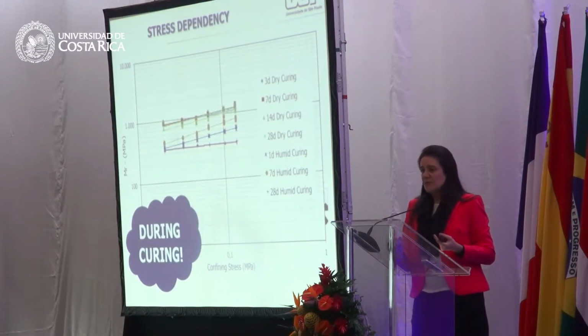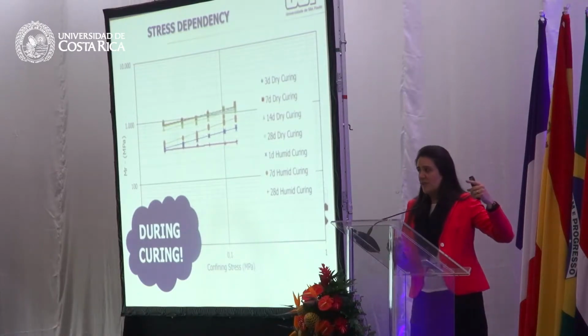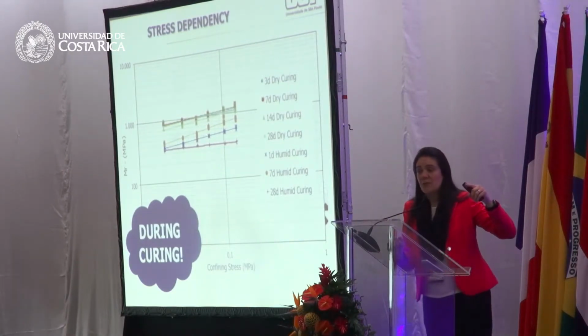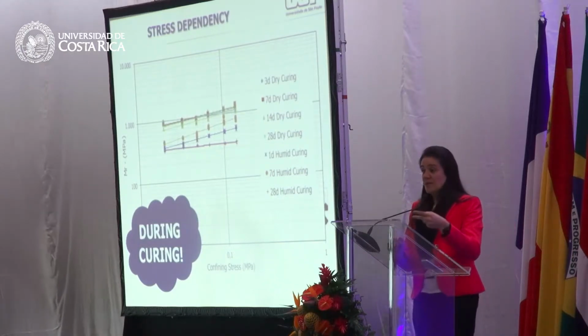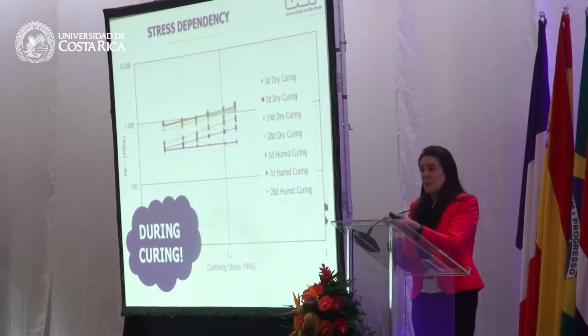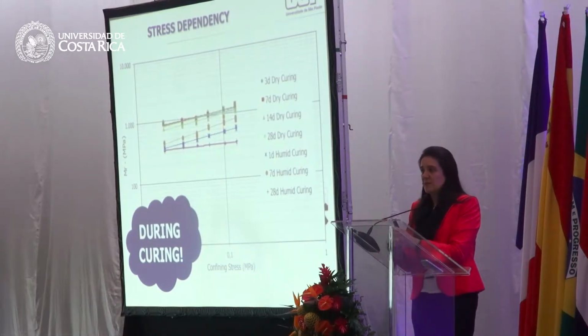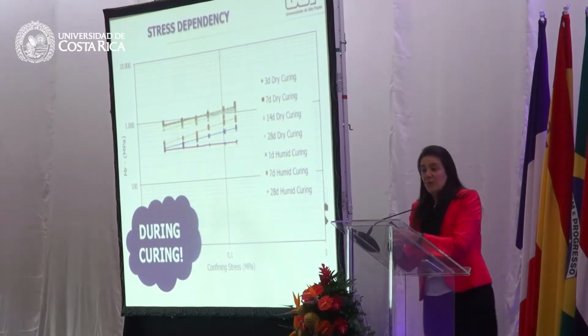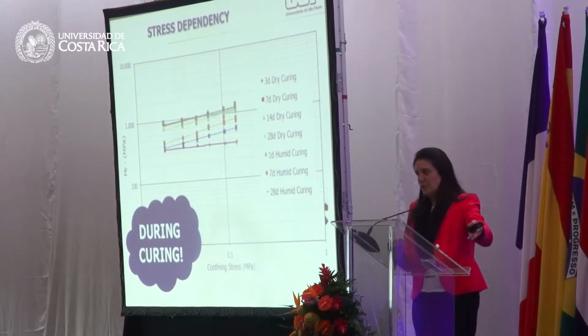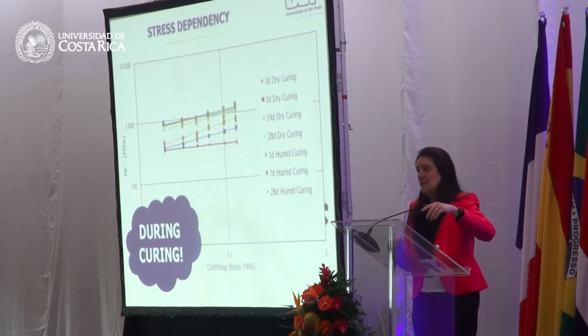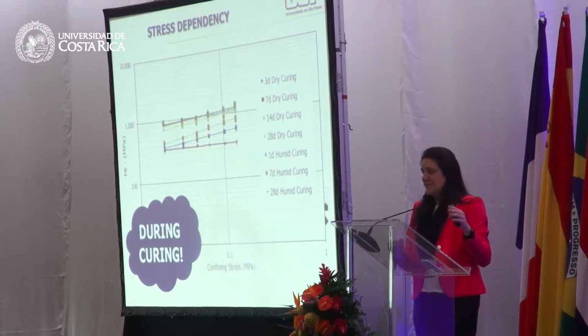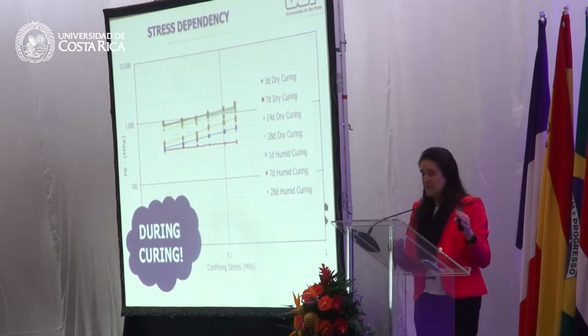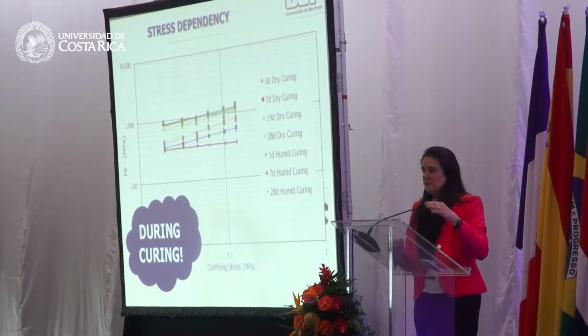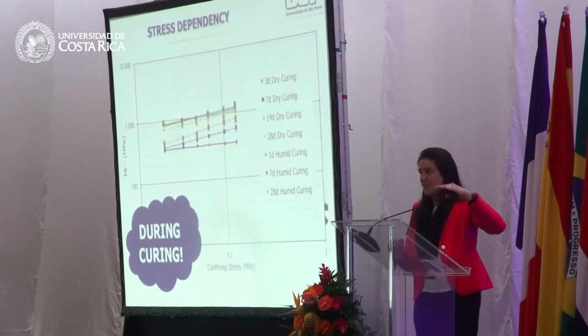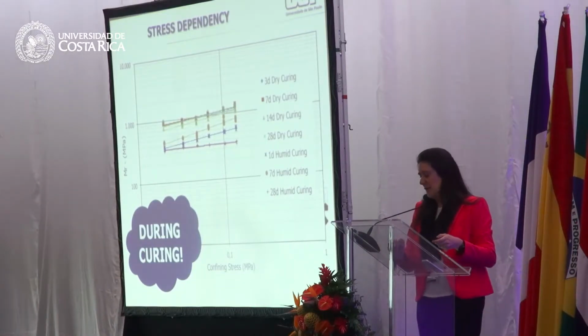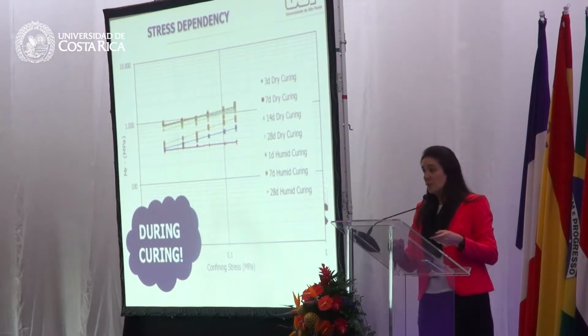So what is the curing process? Remember that I've mentioned we have water in our composition, and it's not only the water that foams the asphalt. It's like the water that you put for a granular material, for compaction. We need that to be able to compact that mix in the field. The water is in there. You put your mixture on the field, you compact it, and the water is still there. It takes some time, and it can be a lot of time, I'm saying months, until this material reaches the equilibrium regarding the water amount. So the curing is very, very important.